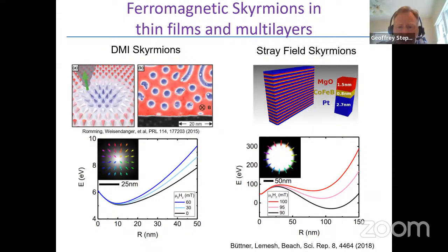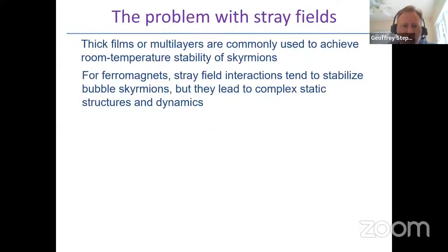But going hand in hand with that is the fact that the stray fields that are responsible for the stability of these kinds of topological structures necessarily lead to much larger magnetic skyrmions than one would desire for applications. Again, typically on the order of tens or even hundreds of nanometers in materials. So that's not desirable. So the stray field interactions make it easier to achieve a magnetic skyrmion, but they really limit the static properties of a magnetic skyrmion.